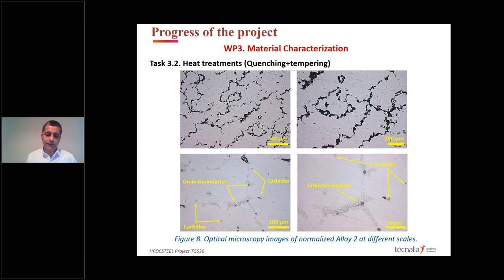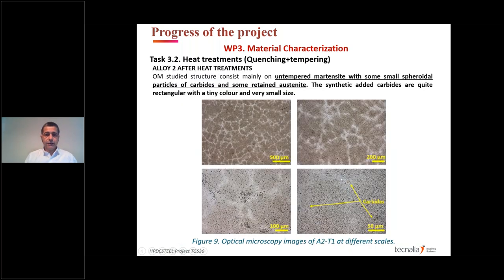of reinforcing master alloy. Here we can see after quenching and tempering which one was the structure. We can see small carbides inside the grains of the steel, also at the grain boundaries, and small carbides over the grain boundaries. So this objective of having small synthetic carbides inside the grains was a good sign. So after the heat treatments, we had an untempered martensite. So it was not completely tempered martensite. We have also some very small, well-distributed synthetic carbides.